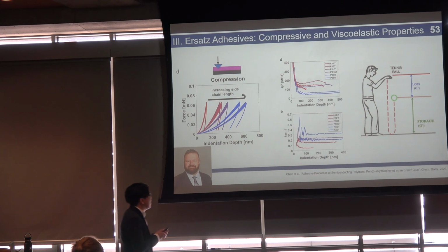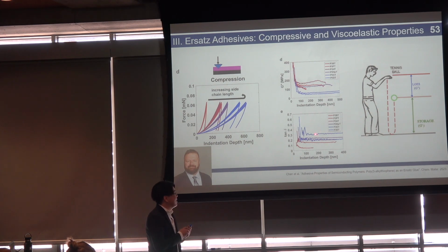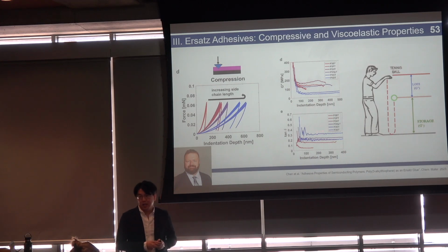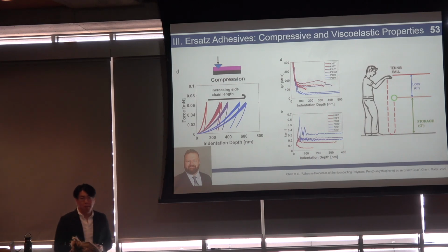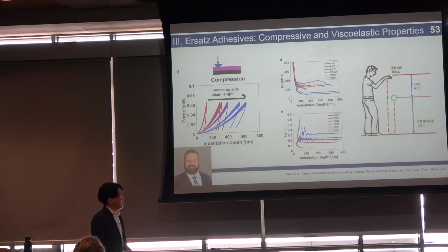And we actually see that the highest viscoelasticity is at n equals 8. So the best viscoelastic properties is, again, not at the longest side chain length, it's at n equals 8.